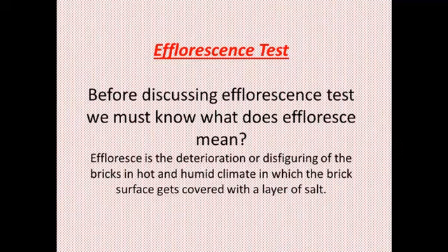After drying, a fresh quantity of water is added, and when the bricks are observed to be dried again, at the second drying each brick is observed for efflorescence. Is there the appearance of white patches of salt on the surface of the brick? The efflorescence may be serious, heavy, moderate, or slight.